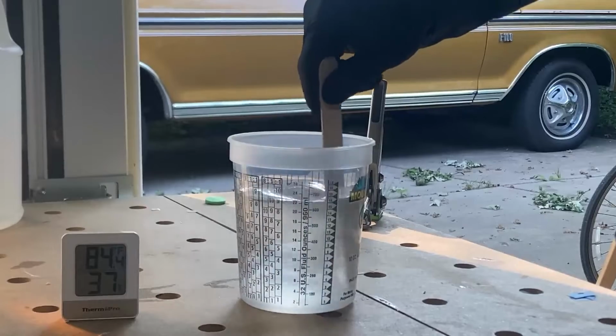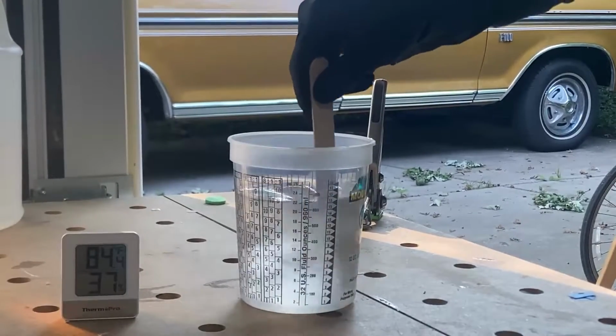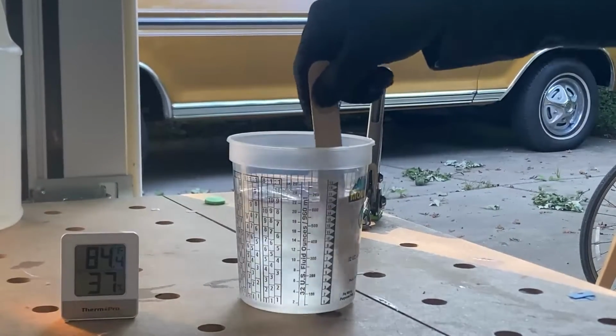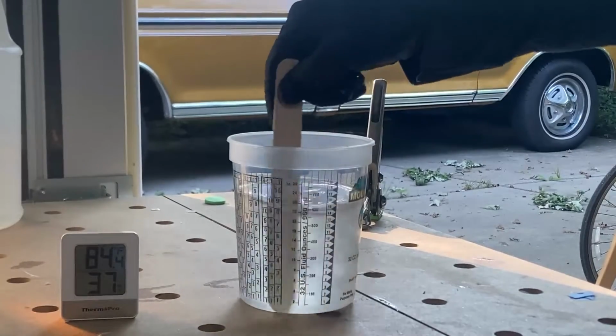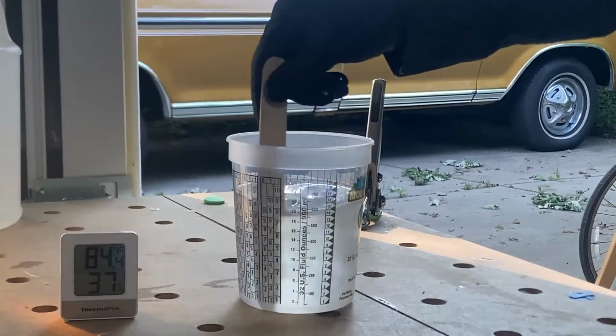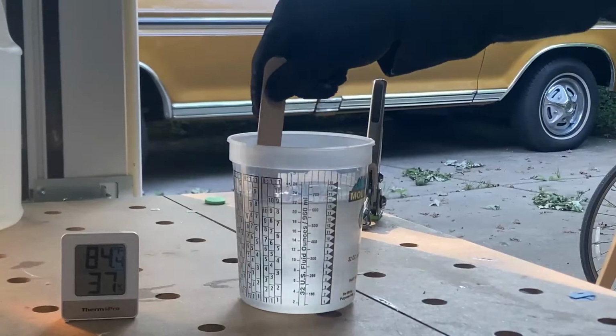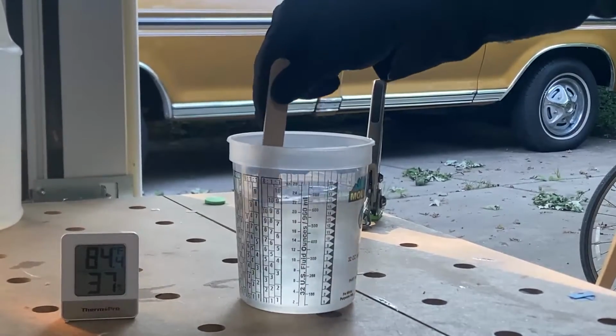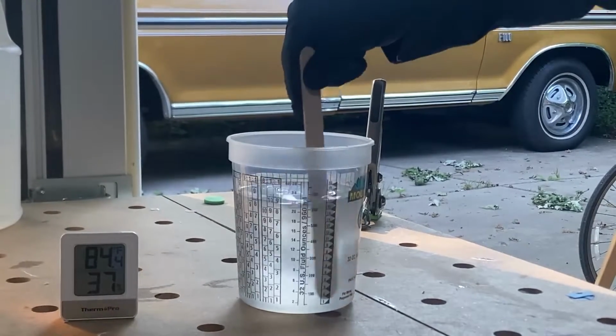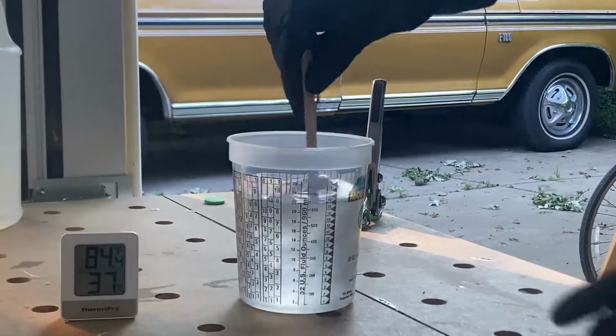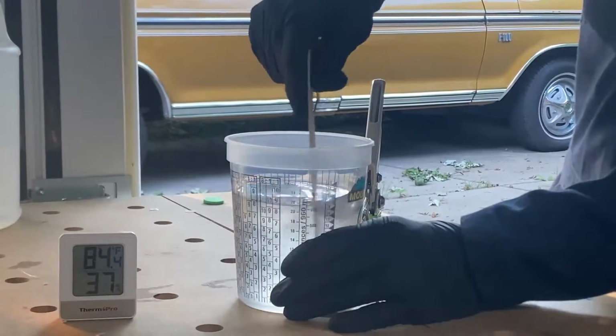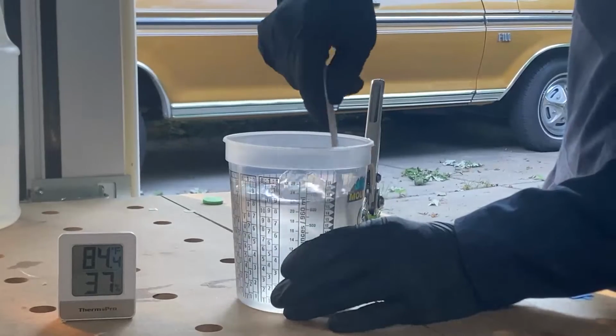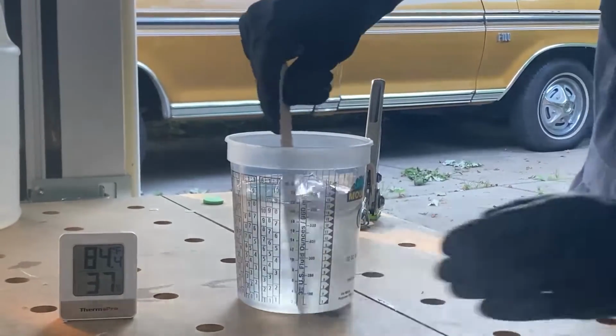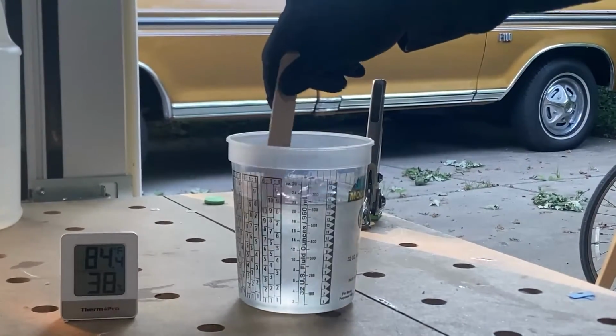A key to avoiding these pinholes, beyond gentle mixing practices, is to start with a board that is preheated, in a sense, and apply the resin as the temperature is dropping. This can be accomplished by adjusting your heating or cooling system if you have one, and if you don't, and maybe you're working in an outdoor garage workshop, try to do this hot coating in the afternoon or the evening as the environmental temperature begins to drop.